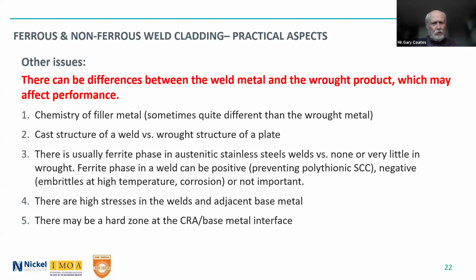And sometimes it's negative because ferrite will embrittle at high temperature, reduce the toughness or the ductility of the material at high temperature. Occasionally, there's cases where it affects corrosion, in which case, if you're welding two plates together, you use a low ferrite filler metal for that, and so that has to be considered here too. Usually, I would say in 90% of the applications, the presence of ferrite is really not important from a perspective of the performance of the clad in service.